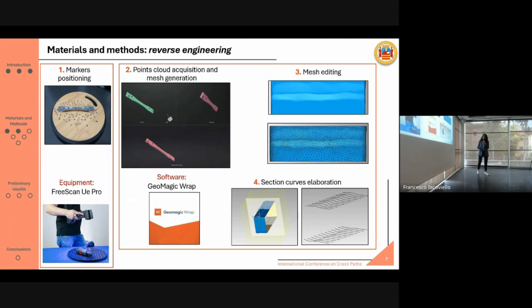So the numerical model was adjusted and a first mesh was created by means of the Geomagic software. Then we focused on the central part of the specimen, around the welding bead. And with cutting planes, we cut this volume in order to obtain all these curves that represented the section of the welding bead for the top and bottom surface of the specimen itself.